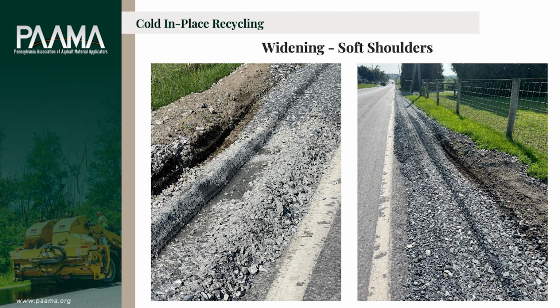As you can see here, this was widened and they added an aggregate to it. The trouble is they didn't do a good stabilization. They didn't get the strength in the base. They had a soft area they should have dug out and they didn't. And that's why all that failed, but it was before we recycled the roadway.